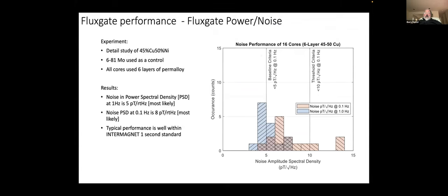David then went on and made a larger collection of these 45% copper permalloys, tested them at 0.1 hertz and at 1 hertz. And here he's plotted a distribution of the results measured at these frequencies.